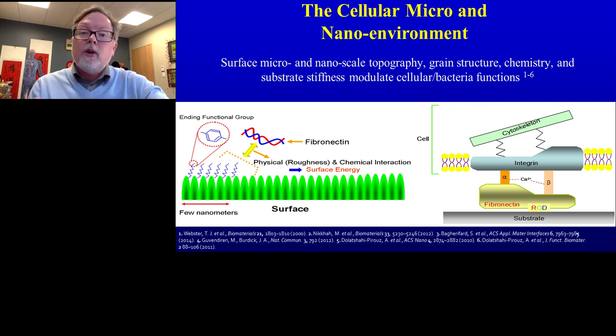Similarly, if we started with a hydrophobic chemistry, like a polymer, and we consider what its energy is when flat versus when it has nanoscale features, we quickly can understand that there's more surface area in that polymer when it has nanoscale features, and that in turn can lead to more hydrophobic interactions because you have more hydrophobic polymer chemistries exposed.